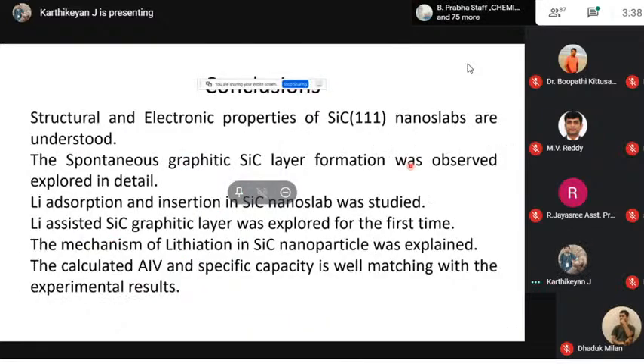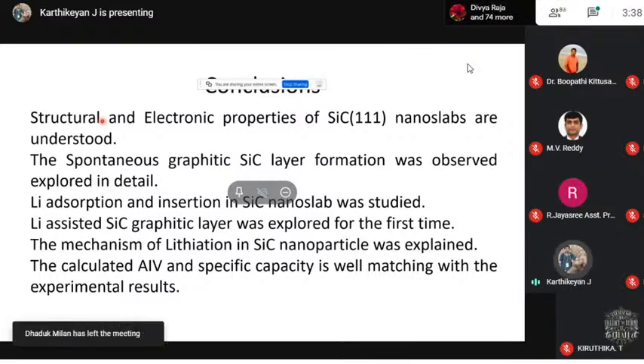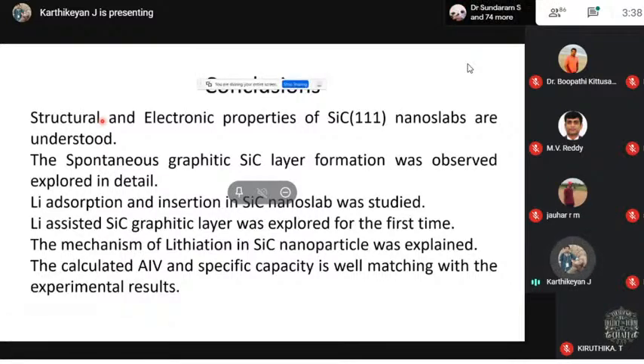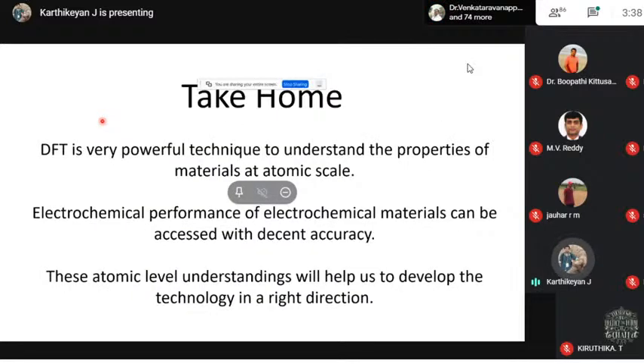electrode materials. So we have actually studied the electronic properties of silicon carbide nanoslabs, and then we understood that even without lithium, it forms a graphitic SiC layer. That was the starting of our work, and we started using lithium for making this graphitic SiC layer, and we understood their electronic properties and their electrochemical properties. So basically, we have calculated the average voltage, that's also matching with the experiment, and the specific capacity is also matching with the experiments. And the take-home message is this: DFT is a very powerful technique to understand the properties of material at nanoscale, or we can say atomic scale.